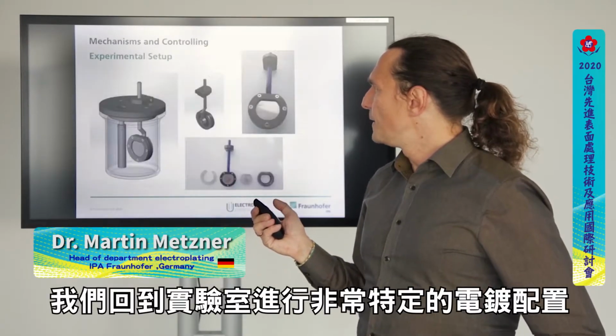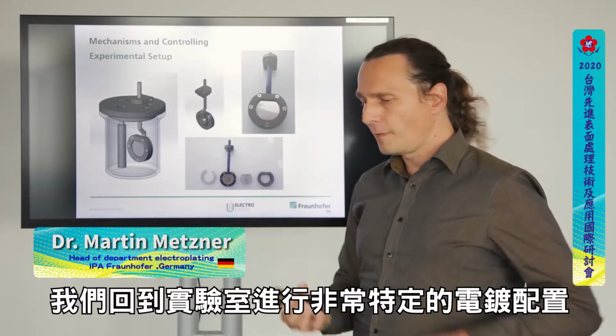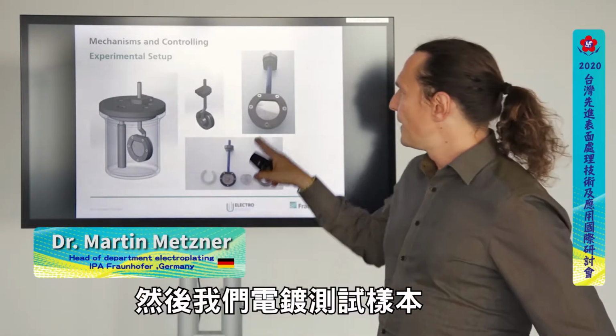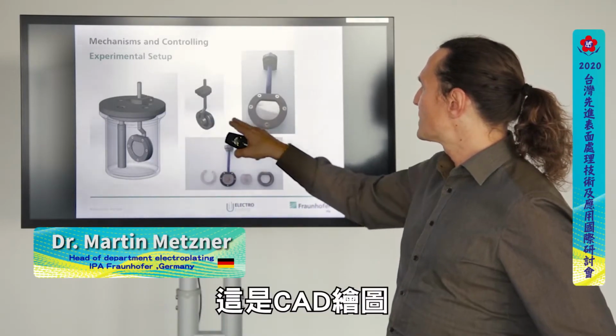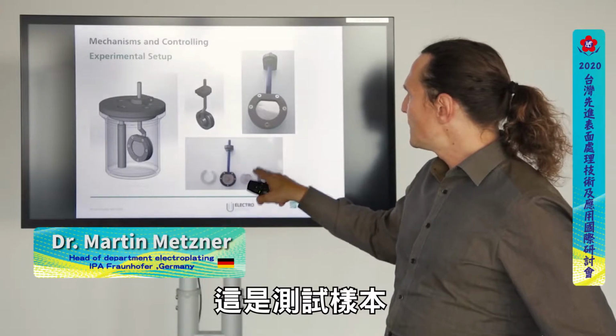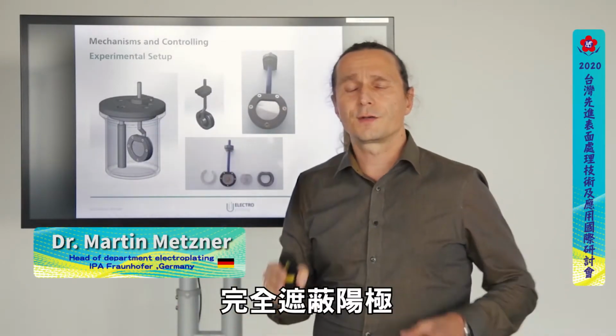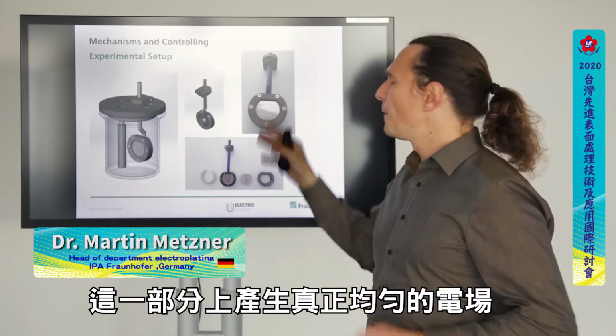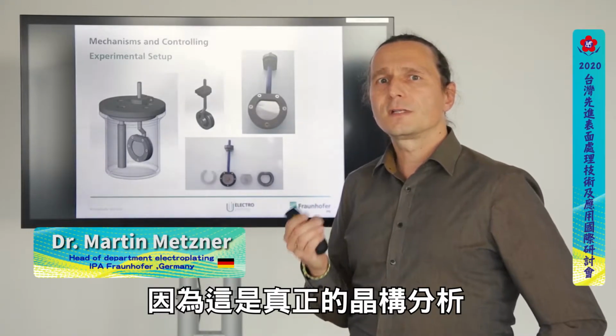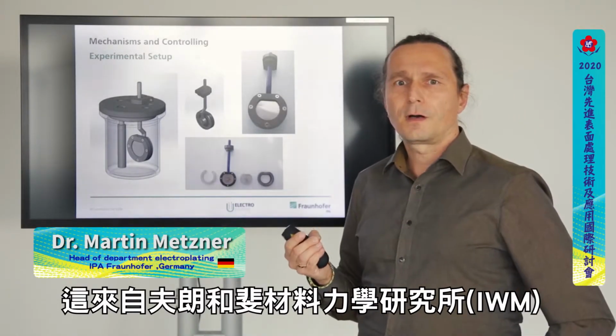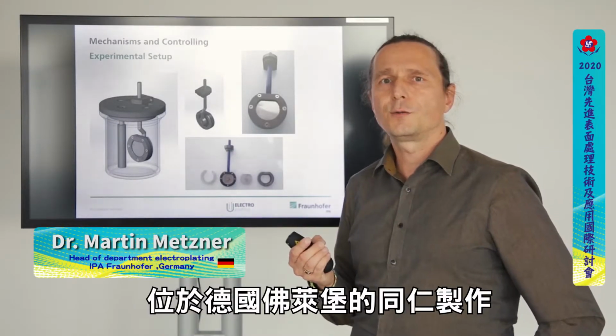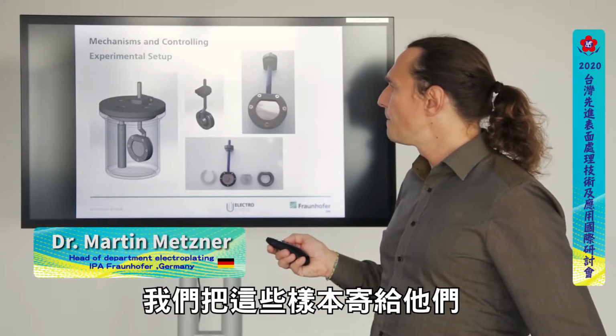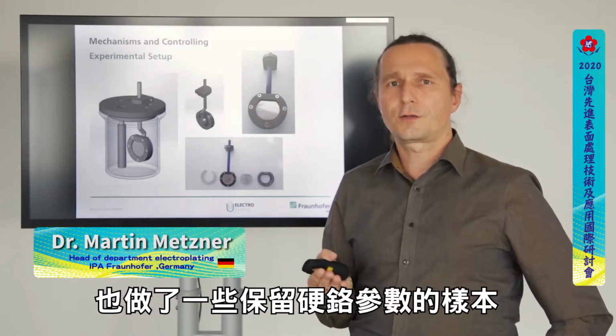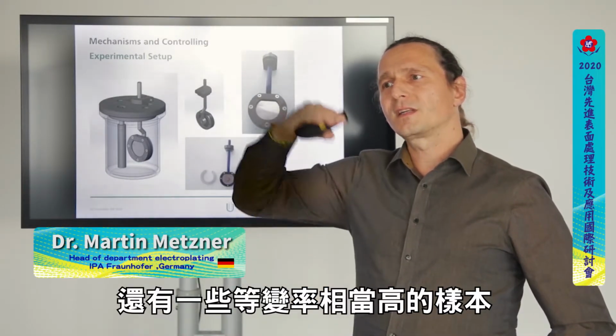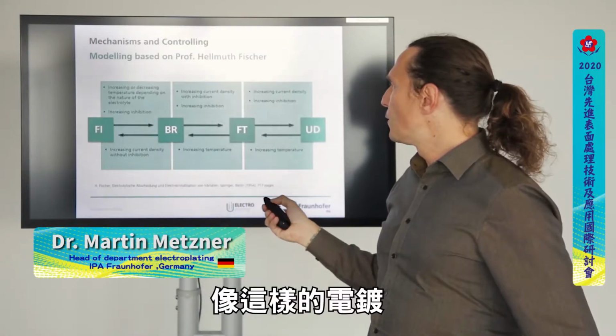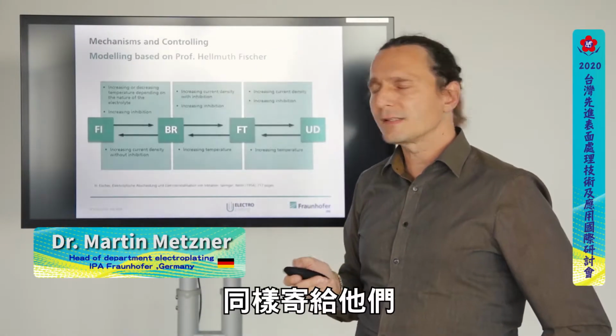And then we went back to a very specific plating setup in our lab with a small beaker, 1.5 liter. And then we plated test samples. So these are CAD drawings, these are the real pictures. This is the test specimen. It was completely shielded against the anodes so that we can have a real homogeneous electric field on these parts that we plated, because this was for real crystalline structure analysis made by our colleagues from Fraunhofer Institute for Mechanics of Materials in Freiburg. So we sent these specimens to them, and we made some specimens where we stayed on the hard chromium parameters, and we made some specimens where we went up to the very high level of our ramp, so where we plated in this way, and also sent this to them.